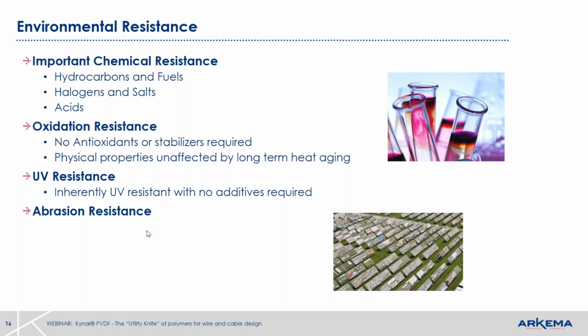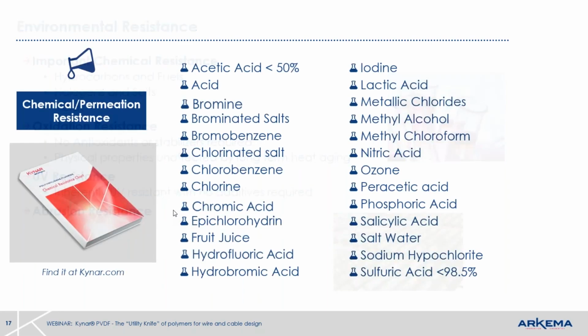Abrasion resistance of PVDF is great, especially the homopolymer grades. The only other polymer that's more abrasion resistant than PVDF is ultra-high molecular weight polyethylene, which is extremely difficult to extrude. So from a cable point of view, PVDF is a very, very tough material and is excellent in abrasion resistance. Here's a list of more chemicals.